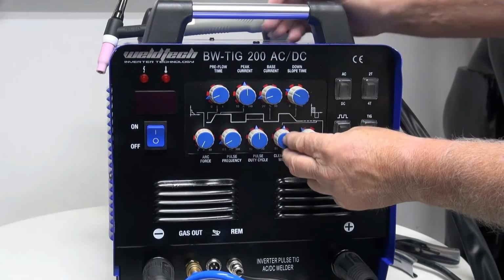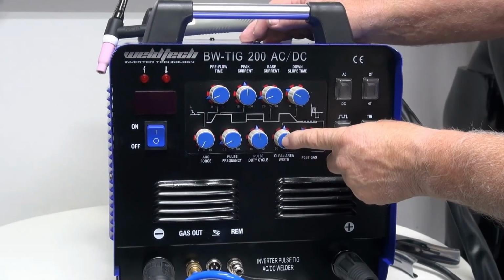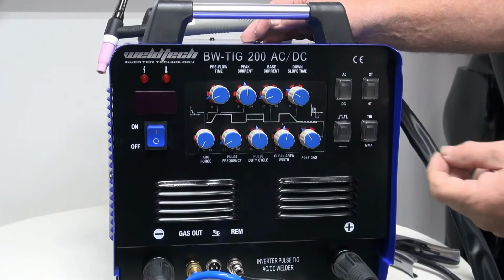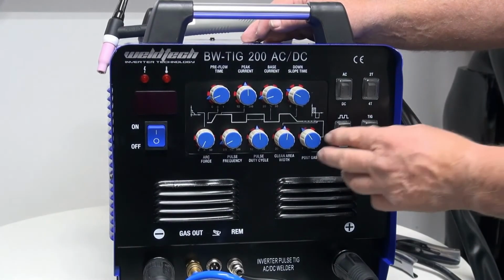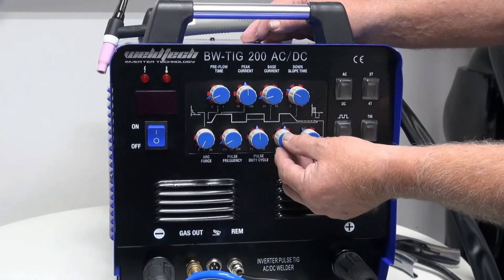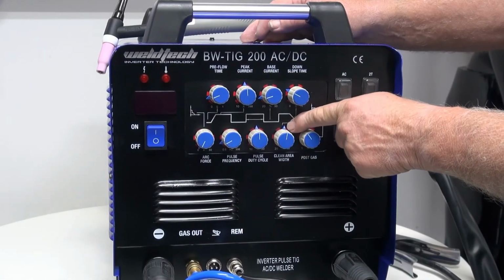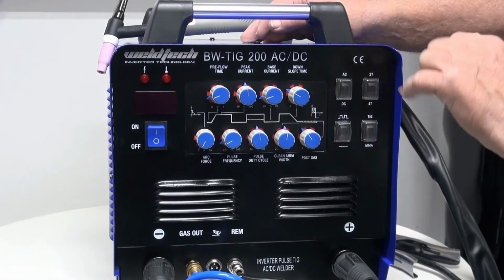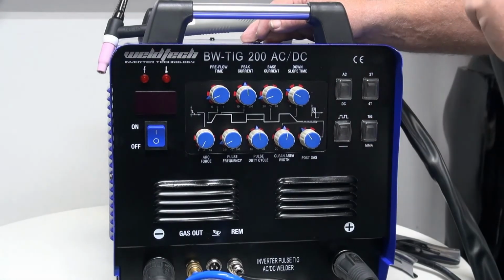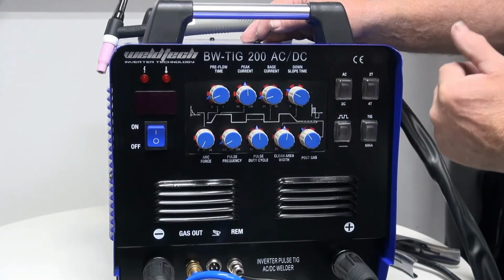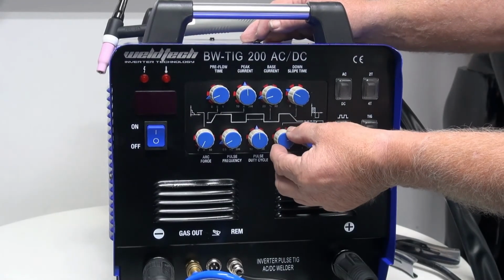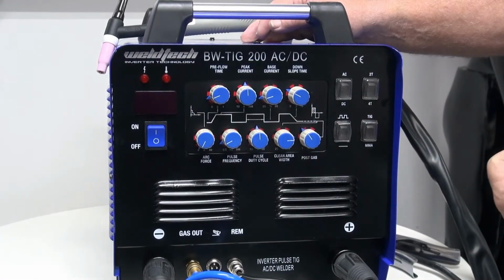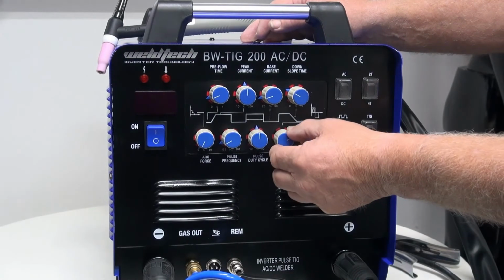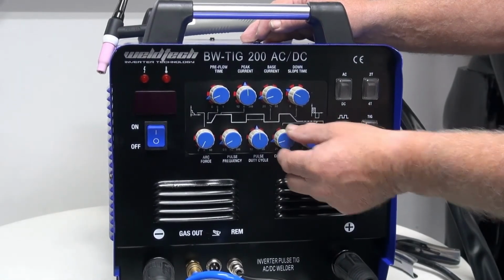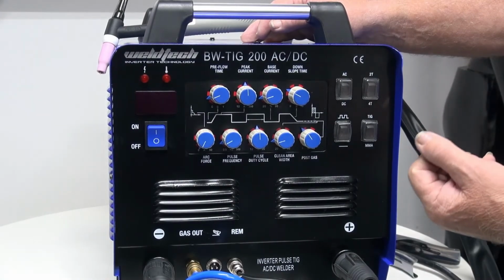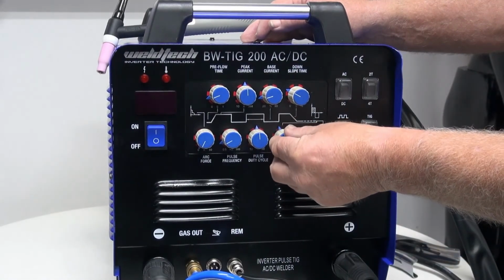This next one along is called AC balance or AC balancing, depending on what terminology you use. When you first set up the welder, I always recommend that you set it up at 50%. Now, this means that the top half of the cycle and the bottom half of the square wave cycle, which I'll show on the board, will be equal. We can unbalance the wave by turning it to the right, and this will give us more heat into the tungsten. If we turn it to the left, this will give us less heat into the tungsten, but more penetration into the workpiece.